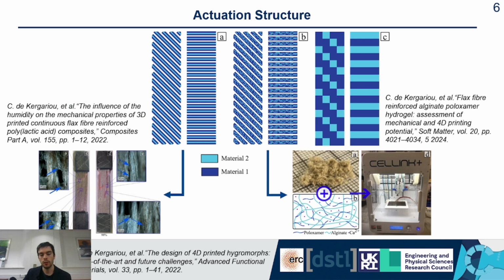So first, we're going to talk about the actuation structures available to create soft robotic actuators. Three different structures are available: continuous fiber composites, discontinuous fiber composites, and biomaterial structures. For A and B, continuous and discontinuous fiber composites, the principle is the same. Basically, you have orthotropic materials. These materials have different properties transverse to the fibers and in the direction of the fibers. So if you print different layers with different fiber directions, then the different layers will have different expansion when in contact with humidity, and therefore you are back in the situation of the pine cone.